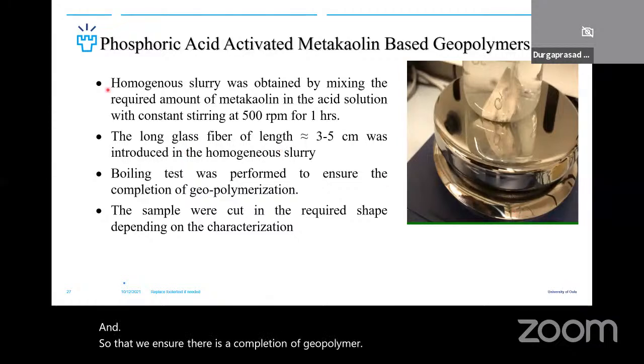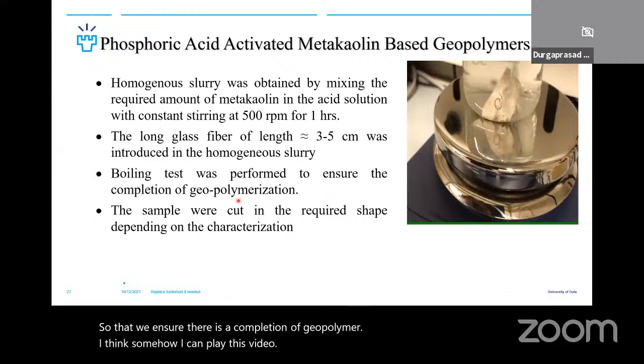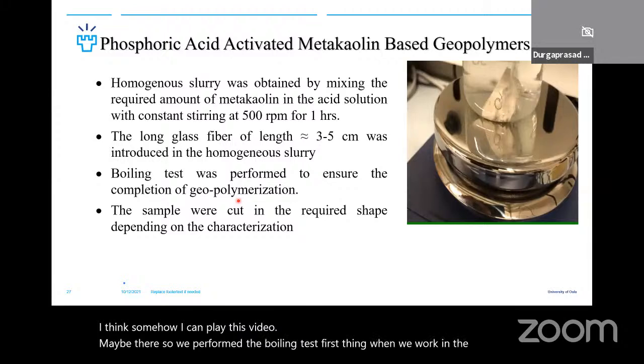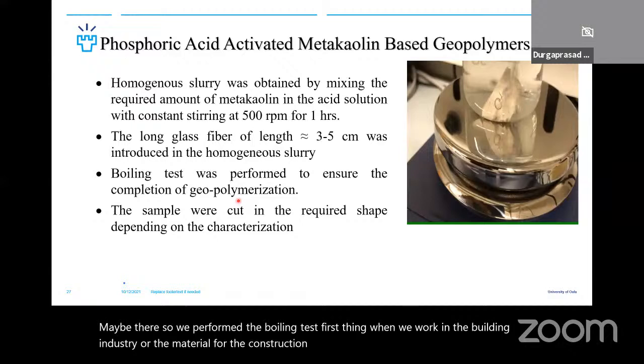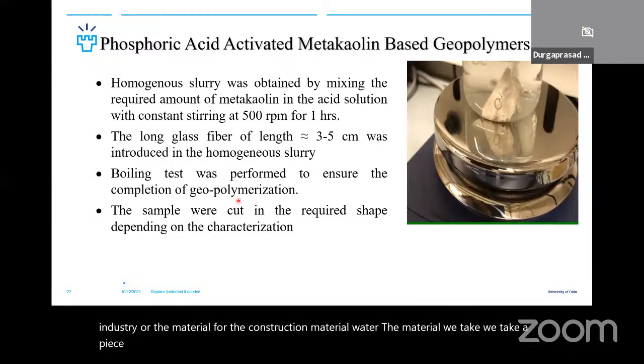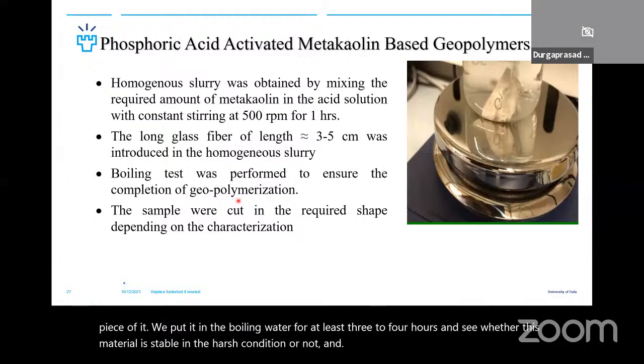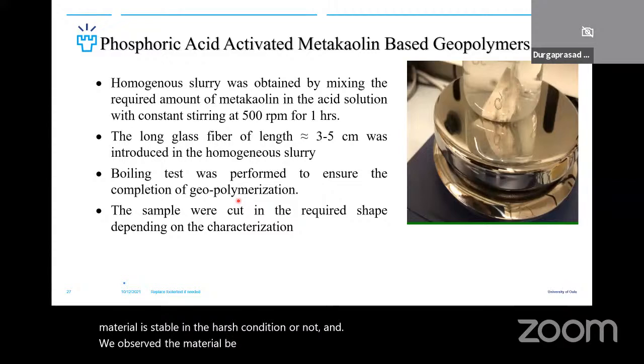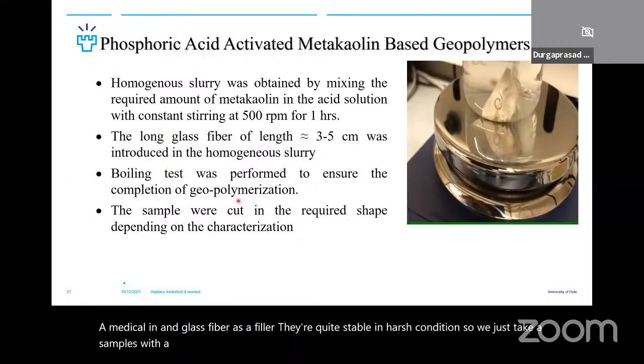I think I can play this video maybe later. So we performed the boiling test. First thing, when we work with construction material, whatever the material, we take a piece of it, put it in boiling water for at least 3 to 4 hours, and see whether this material is stable in harsh conditions or not. And we observed that the material we prepared with metakaolin and glass fiber as a filler is quite stable in harsh conditions. So we take samples with different shapes, cut them and use them for further work.